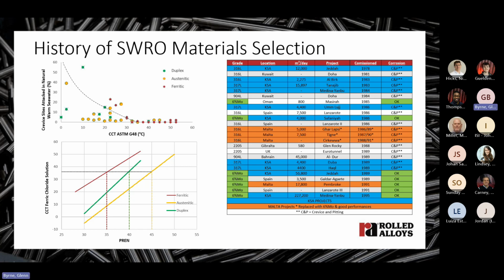In some applications, the performance of low-grade stainless steel was quite catastrophic, corroded very quickly. If you look at these three projects in Malta, 316 was installed in 1986, and by 1989, it had to be replaced with 6% molybdenum alloys. Again, in 1987, this particular project built in 316, and by 1990, it had to be replaced with 6% molybdenum alloy. And similarly, for this job, in 1988, it was built in 316, and by 1991, it was replaced. Once it was replaced with 6MO, the performance was very good.